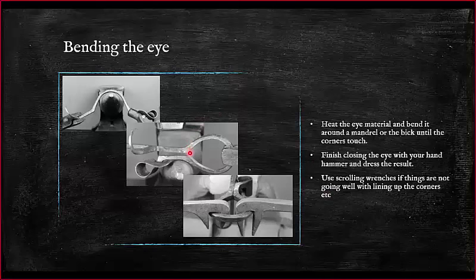You want the heat no further. Do you want it to end here and come all the way around and end here? Or do you even want it back here? No, I would heat the whole eye. And I don't mind it going a little bit into those straighter sections. Remember, the corner is going to act as a resist. It has more material than anything else. So it's going to anchor the material. You're not going to change that bend terribly much, because everything else is going to change because it's thinner. If it's all heated equally. Now, if you've got no heat in the eye and the corner is the only bit that's hot, then yes, the corner will move. But if everything's hot, it's going to bend where it's most convenient. And that's where the stock is thinnest. And that's going to be where you put those chamfers on the side of the eye.